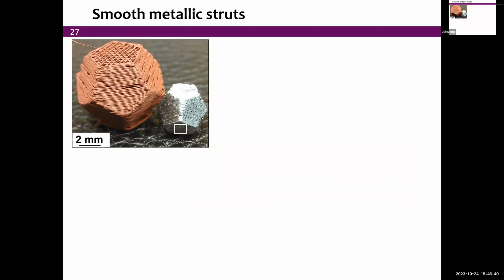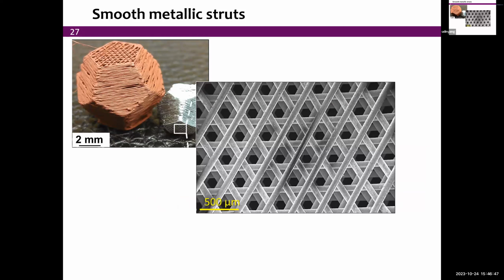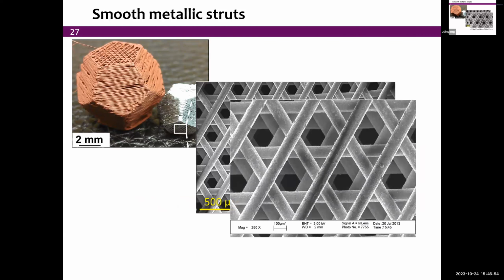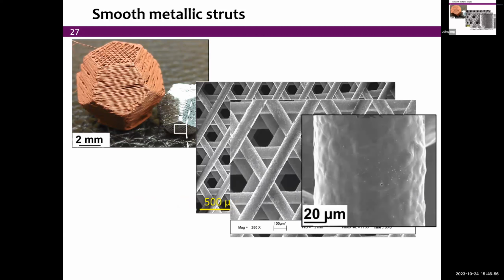Now, let's look a little bit at the quality of the printing that is achieved after this reduction and sintering. So this is SEM. You see extremely smooth struts, as we call them, in this lattice. And if you go to even higher and higher magnification, you see how extremely smooth and notch-free the material is. That's because we are using sub-micron particles, tiny, even to that 20 micron, that all sinter and create those smooth surfaces. You may see a few grooves here due to grain boundaries.